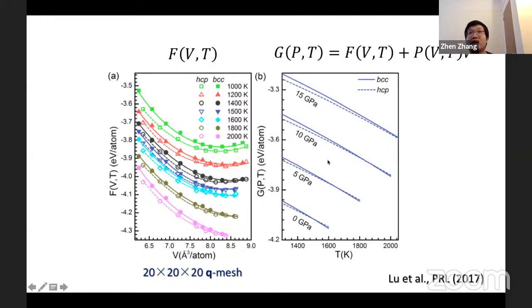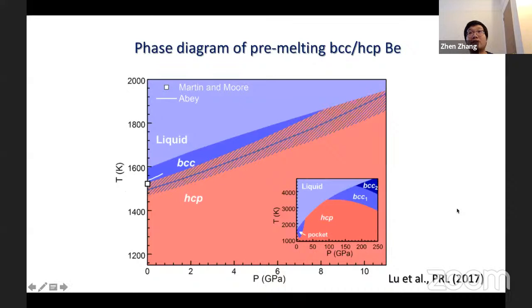To obtain the phase boundary, Gibbs free energy is desired. Therefore, Gibbs free energy was obtained by adding the PV term to F, and the free energies as a function of Vt were converted to functions of Pt by using the equation of states. By comparing the Gibbs free energies for both phases, the pre-melting phase boundary between BCC and HCP structure were obtained at the low pressure range. The shaded area here indicates the computational uncertainties. Accurate free energy calculations by the present phonon quasi-particle approach enable the discovery of a narrow region where BCC structure is stable before melting.